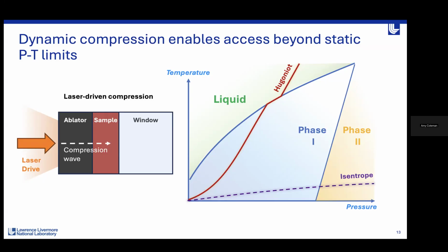And as this compression wave enters our target, it transits through the ablator, progresses forward, compressing everything as it goes, enters the sample, traverses the sample, and so we compress this whole package that way. Now, just to give an idea of the scale of this type of experiment, typically the layers in this physics package are on the order of microns, tens of microns, and our laser driver is on the order of nanoseconds or tens of nanoseconds. So these experiments are very small and they're very, very quick.